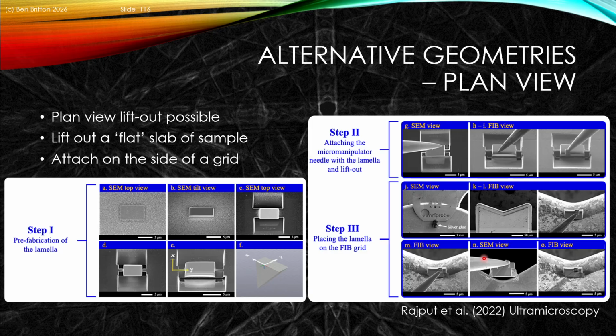Now, FIB lift-out doesn't have to be done always in cross-section. We can also do a so-called plan view, and this can be particularly useful when you want to look at the surface of a particular component, or for instance, a grown structure. So you can do a deposition, and effectively you can deposit on the top layer, and then what you do is you basically produce a very thin section out of this material.